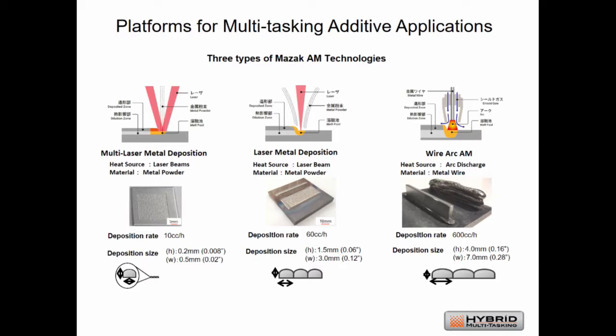This gives you a clear, I don't know if you can see along the bottom there, the deposition rate for each one of these processes. So the multi-laser is about 10 cubic centimeters per hour, jumping up to 60 cubic centimeters with a single laser, and then jumping up to 600 cubic centimeters for the wire arc system. It also gives you the dimension of each bead as you're laying it down. The other thing that's important is the penetration of the weld going into the substrate. The multi-laser doesn't penetrate into the substrate nearly as much as the wire arc system does. The reason is the wire arc gets heated up a little bit further.